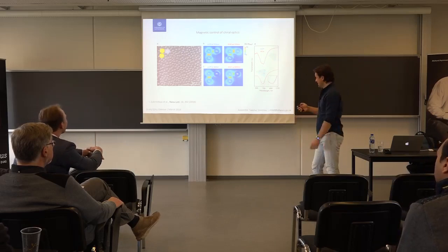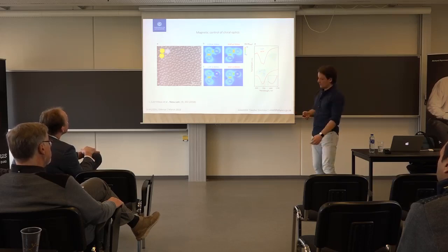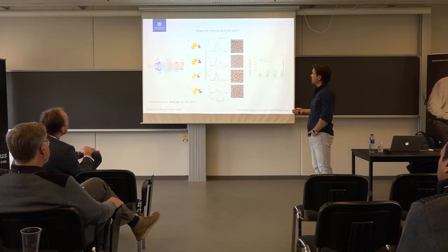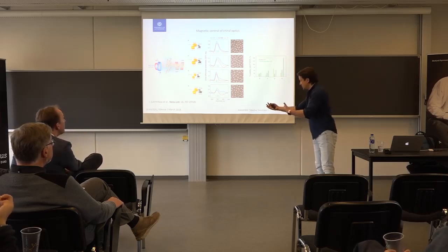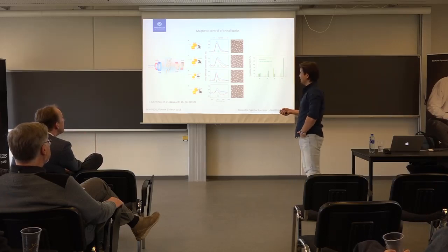So the thing is that when you add the ferromagnetic elements, not only do you break the symmetry, but you also get this dynamic tunability. And this is how you essentially get it. So if you look here, this is the schematics of what we're doing. There is circularly polarized light that comes in, and then we apply a magnetic field to that surface. So gray here is the differential transmission from this surface when there is no magnetic field. And then you start applying plus or minus magnetic field, which is in this case out of plane, and that is the tunability that you get.